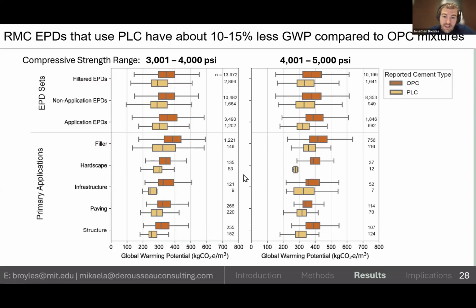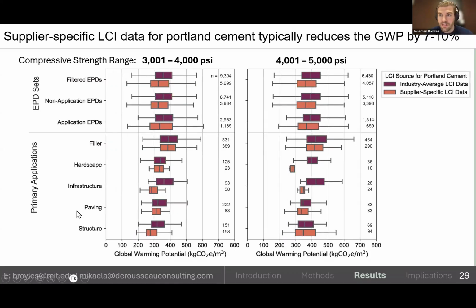I mean, you can kind of see here, fillers, there are about 10% of EPDs that do, a little bit more when you consider the 4,001 to 5,000 PSI strength range. Paving, a lot of paving EPDs in our analysis did use PLC compared to OPC, which we found was interesting, and then a number of structural EPDs too. But again, there's no clear distinction that there are EPDs or applications that definitely do or don't use PLC, except for maybe infrastructure. So that was another interesting finding.